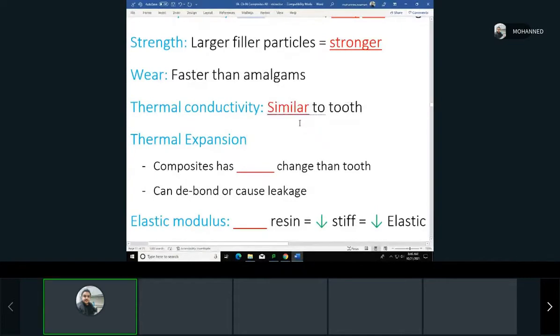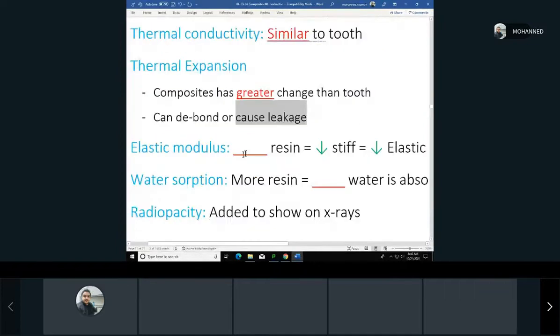Thermal conductivity is similar to the tooth. So it conducts the temperature technically similar to our tooth. Gold is the best one with the thermal conductivity and expansion. Thermal expansion, it has greater expansion than the tooth. And definitely when it has expansion, more expansion means also more contraction. So it can actually debond or can cause leakage. Again, these are like secondary problems with composite because at the end of the day, it's two materials, our tooth and then another material linked to it. So if they change in dimension when we have heat or cold, it can definitely cause some debonding or delinking of the parts. The more the resin, the less stiff and the lower the elastic modulus.